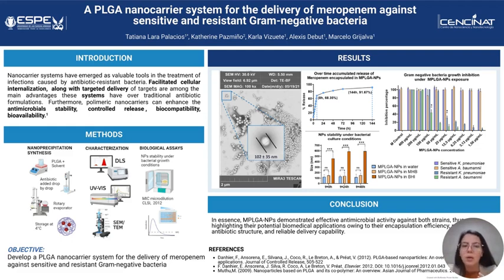In this study, we used the nanoprecipitation method to synthesize poly(lactic-co-glycolic acid) polymeric nanoparticles for encapsulating meropenem, where the meropenem solution was added dropwise to the polymeric solution to form an emulsion, and then was sonicated to reduce the droplet size. Next, the organic solvent was evaporated and the nanoparticles were washed to remove any residual solvent or reagent.